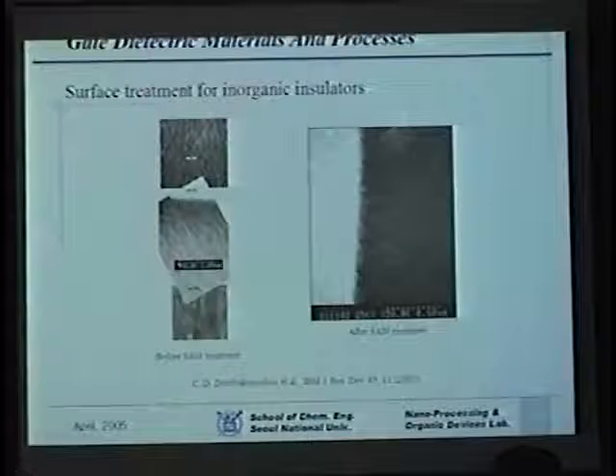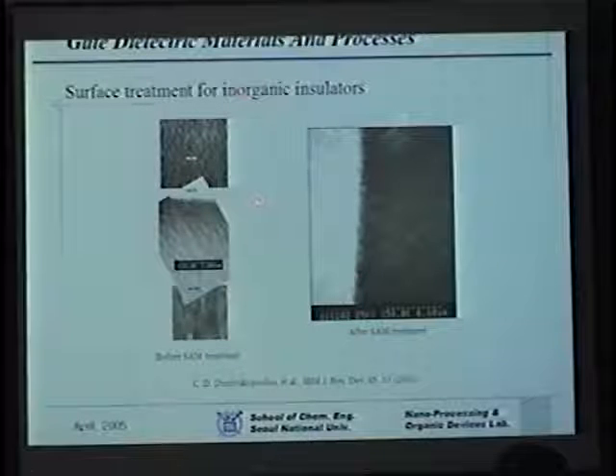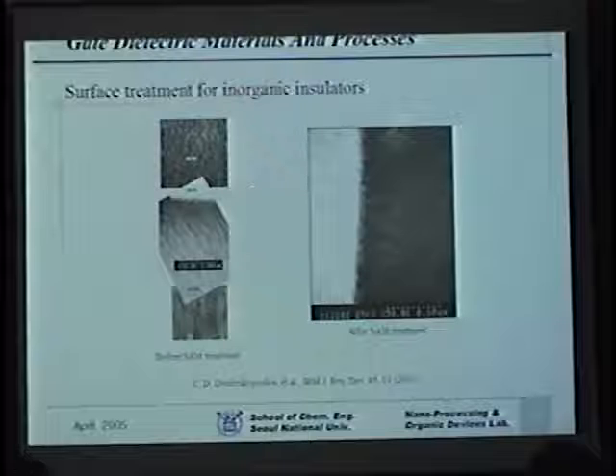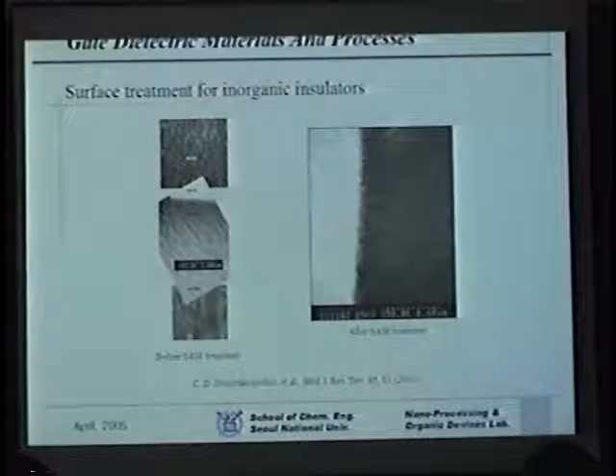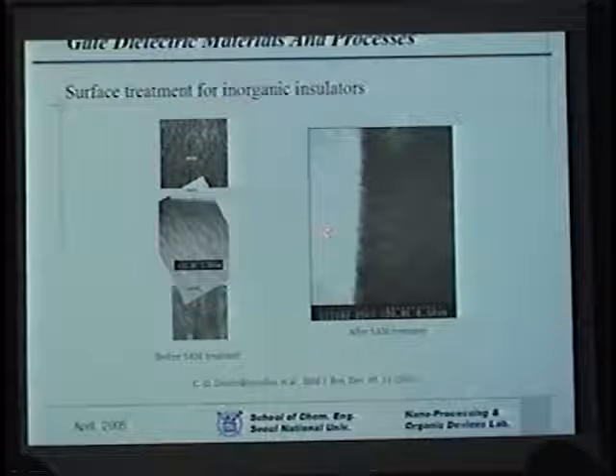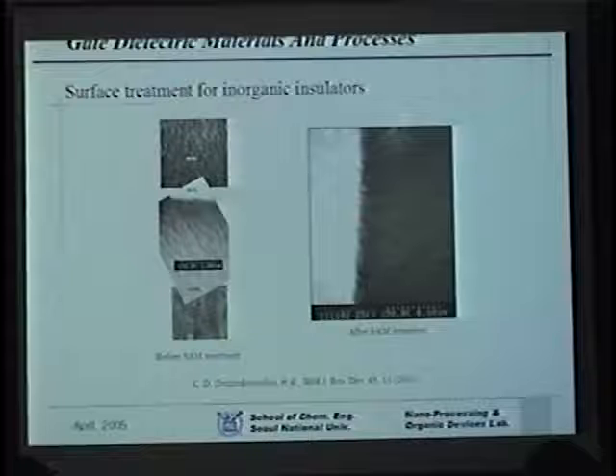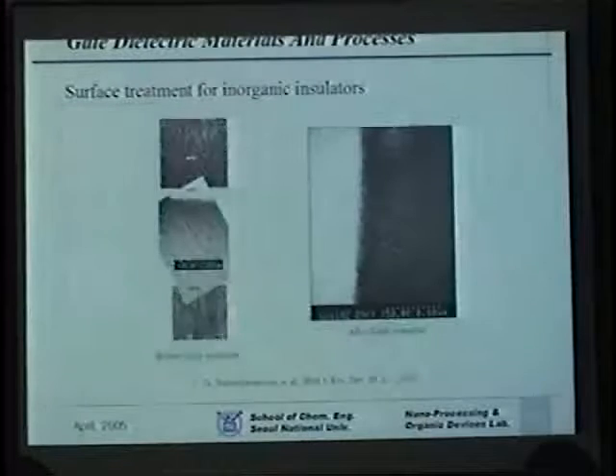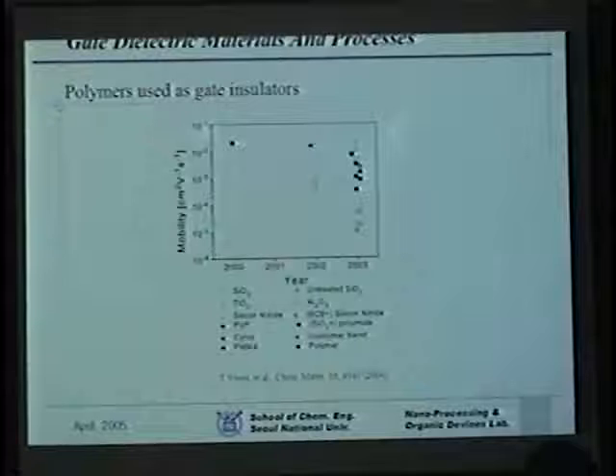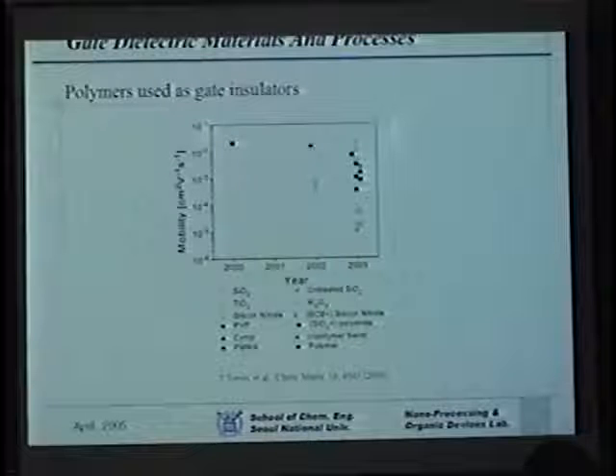One example here is how the grain size of pentacene deposited on SiO2 can be changed. By treating the surface with a self-assembled material, the grain size, although not that well shown here, is the same on the electrode as well as on the insulator, whereas when not treated, they are different. In the case of polymer used as gate insulator, as I indicated before, it's still in the range between 10 to the minus 1 and 10 to the minus 2.